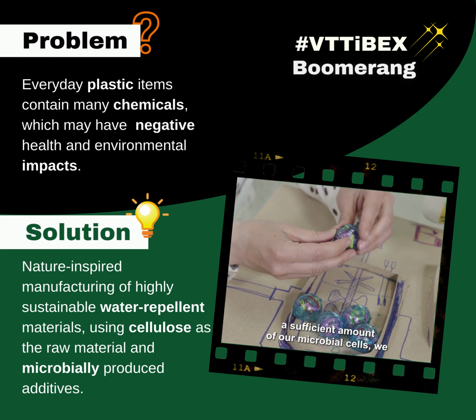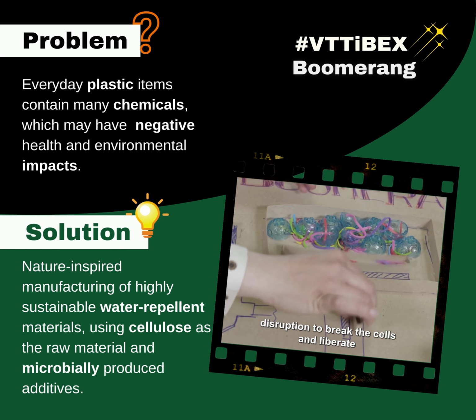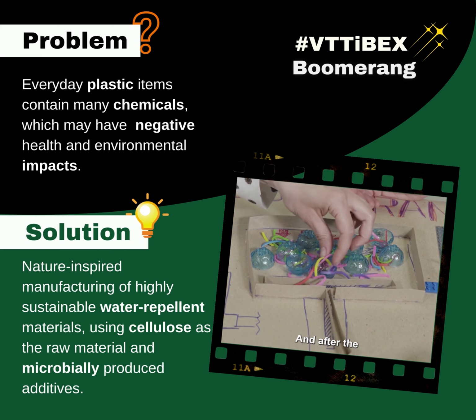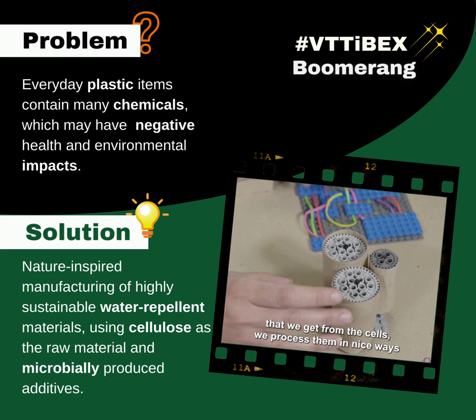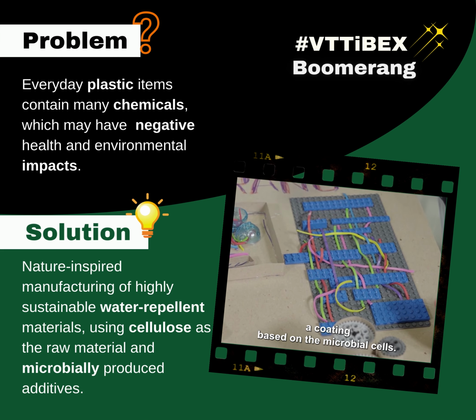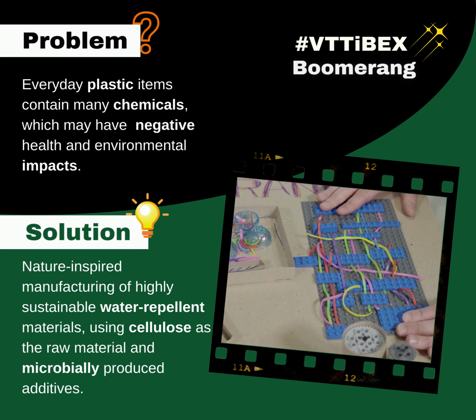After we have been producing a sufficient amount of our microbial cells, we take the cells to a mechanical disruption. So the aim is to break the cells and liberate the polymers that we have inside the cells. And after the mechanical action, we take the components that we get from the cells, we process them in nice ways, and find a perfect way to formulate a coating based on the microbial cells. And there we have the fatty acids that bring the hydrophobicity for our coating, and these blue things represent cell walls of the microbes.